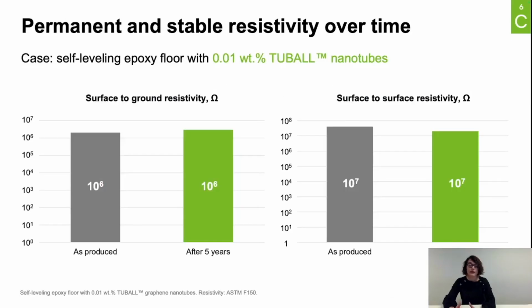Another very interesting chart here is showing the permanent and stable resistivity over time. As I mentioned previously, you will have this 3D network of TUBALL particles within your polymer. That means that you will be able to obtain a surface resistivity as well as a volume resistivity. And as you can see here, tested after 5 years, we are obtaining exactly the same resistivity level as when we produced it 5 years earlier. So 10^6 in surface to ground resistivity and 10^7 in surface to surface resistivity.